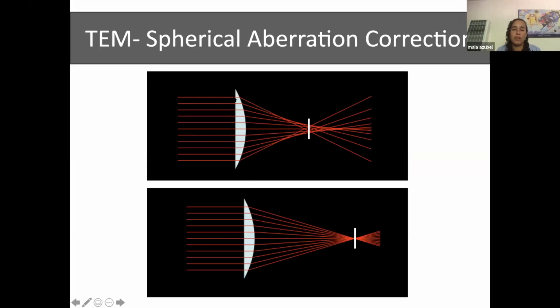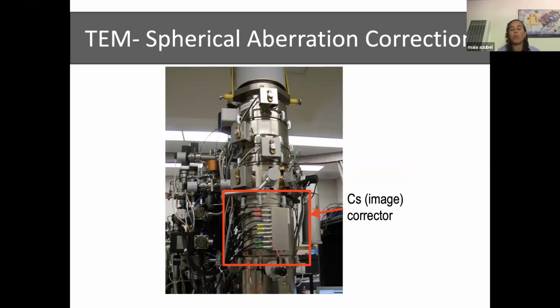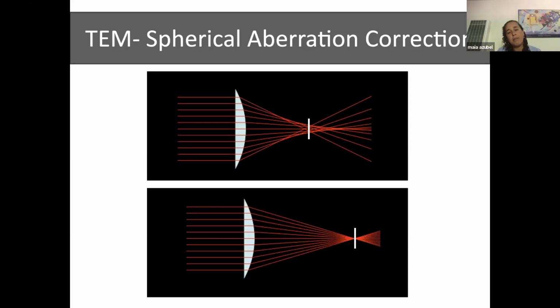When you have a beam of electrons that is crossing the lenses closer to the edge and not to the middle, those, after they cross, are deflected more pronouncedly. So instead of having a focal plane where all the information converges to a single point, which gives you good resolution, you have this fuzzy image. And this is part of the issues that you have, and you will have also in a light microscope. It's just that you're working at a different resolution, and it has to do with the fact that the lenses are not perfect. So the aberration corrector, in a very clever way, inserts different elements that make the beam change direction in a way that when they converge, they will converge in a single point.